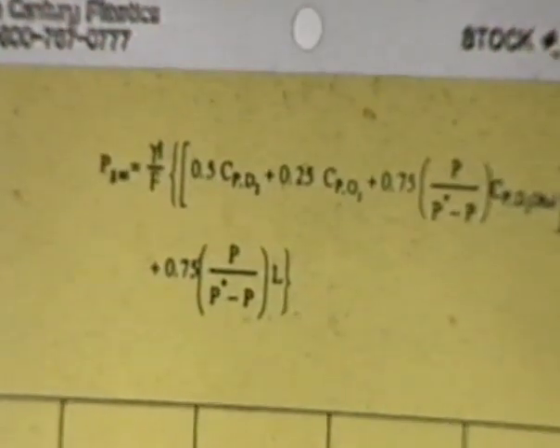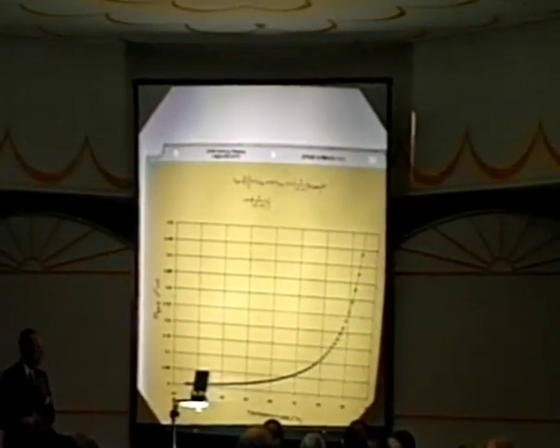To evaluate this, you need to know the heat capacities as a function of whatever the temperature is. So these are the equations that we use for the heat capacity as a function of the temperature. And this shows how the gas term, the power carried away by the gases, can become important at higher temperatures. If you're working around 50 degrees, maybe you don't need to worry too much about the power carried away by the deuterium gas and the oxygen gas and the D2O vapor coming off. But as you go to higher temperatures, you have to be very concerned about it. It can become very large. And that's mainly because of the evaporation, the latent heat of evaporation of the D2O itself.